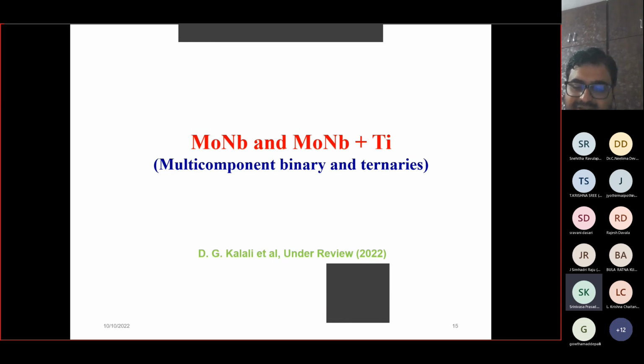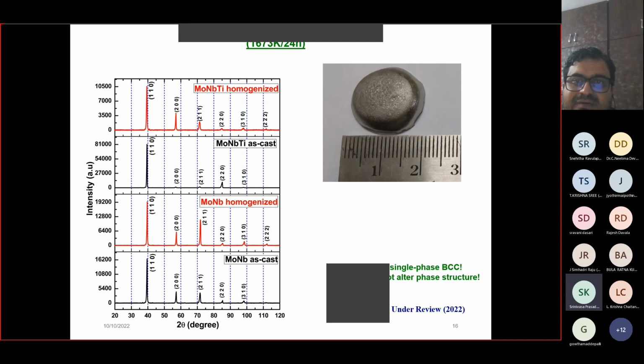And to understand the influence of titanium, because we have just seen that titanium has done really wonders. It gave us extremely high hardness and extremely high density-normalized hardness. Then we wanted to see, and this work is in review now, we have made two systems. One is binary, that is molybdenum-niobium 50-50, and the ternary molybdenum-niobium-titanium 33, 33, and 33. So this is the sample we made using vacuum arc melting, and then we also homogenized these samples at 1400 degrees centigrade for about a day.